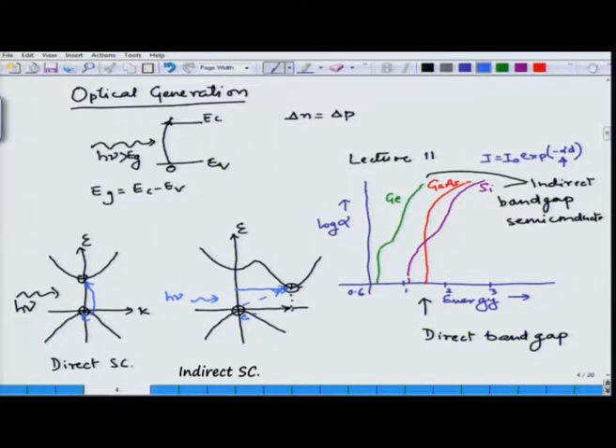a photon, an electron in the valence band and the phonon interacting together then leads to absorption in the case of an indirect band gap semiconductor. Hence at the value of the band gap, if I take the case of silicon, the absorption coefficient initially is very small, but as soon as I reach the point where the energy is about the point where I do not need any change in the momentum in order to go from the valence band to the conduction band, at that point the absorption coefficient increases the way it would have in the case of a direct band gap semiconductor.